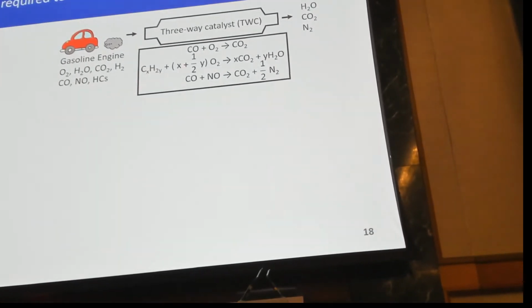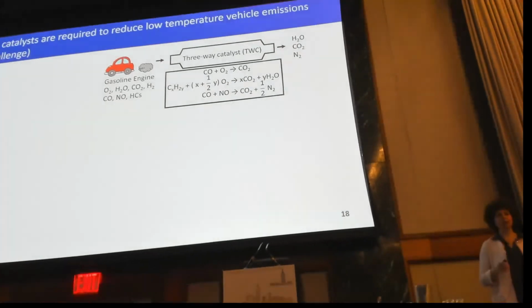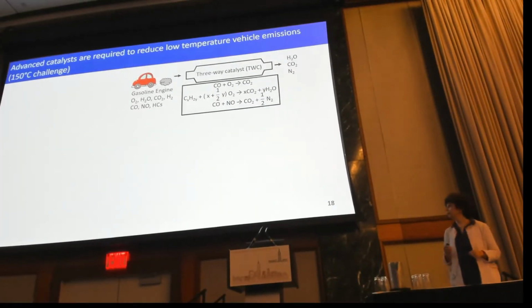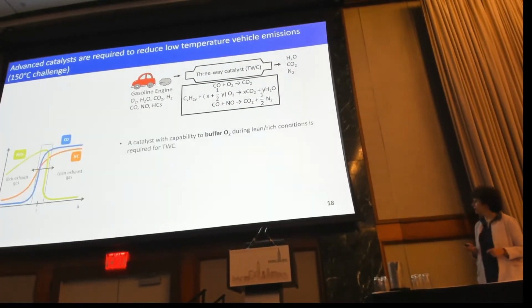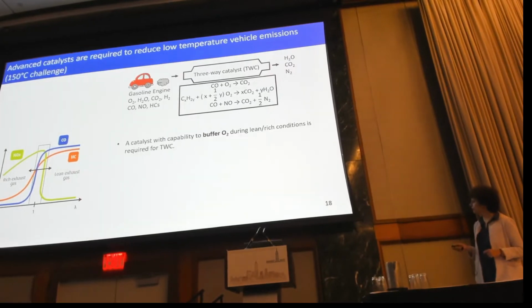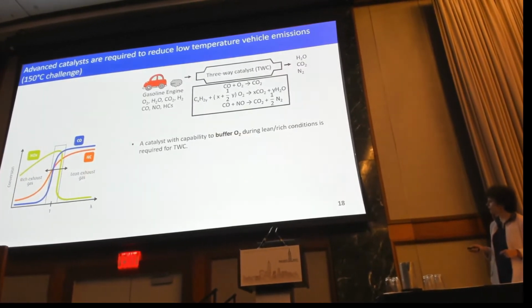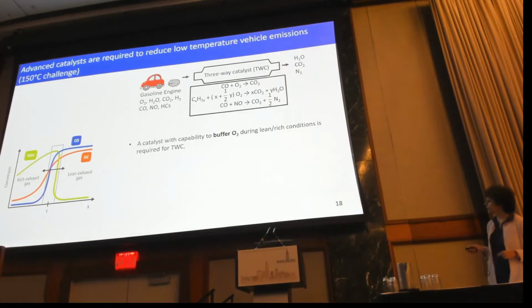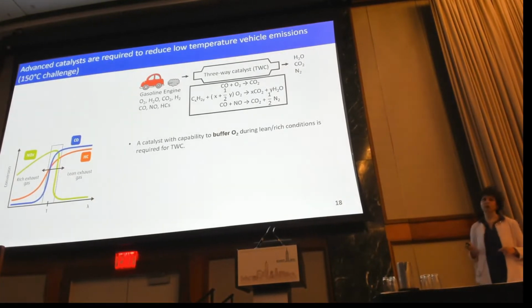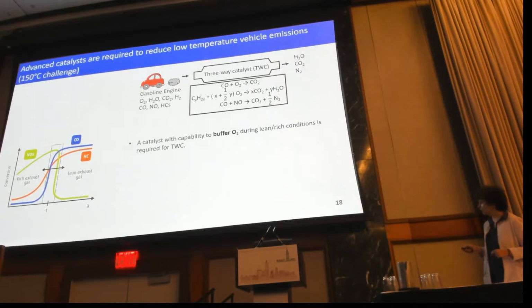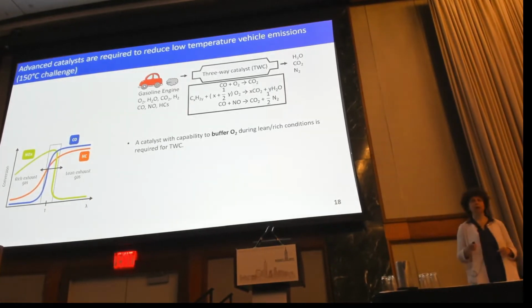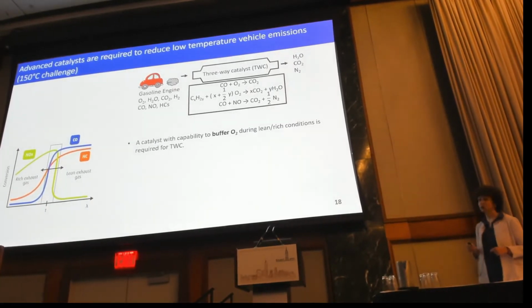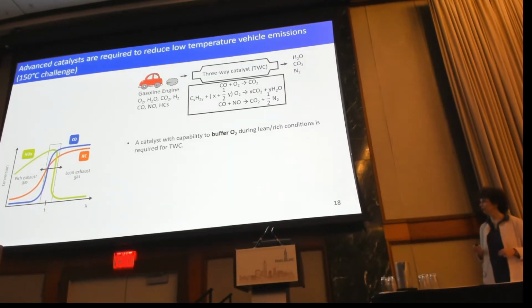So here is a series of the reactions that are taking place in gasoline vehicles. Gasoline vehicles operate under a stoichiometric amount of oxygen. So when we have excess oxygen, the NOx conversion is suppressed. When we don't have enough oxygen, the hydrocarbon and CO conversion is suppressed. So basically, a stoichiometric amount of oxygen seems to be the optimum amount for NOx, CO, and hydrocarbon conversion to occur.